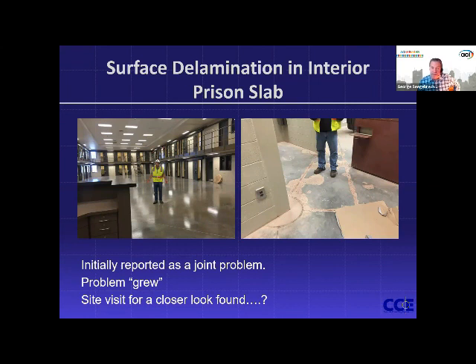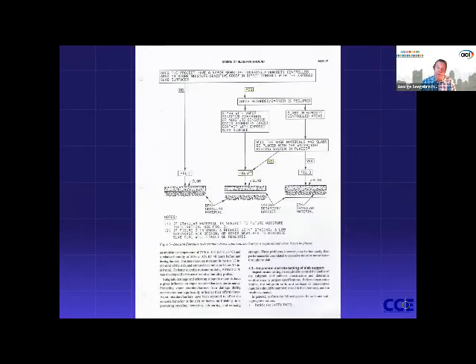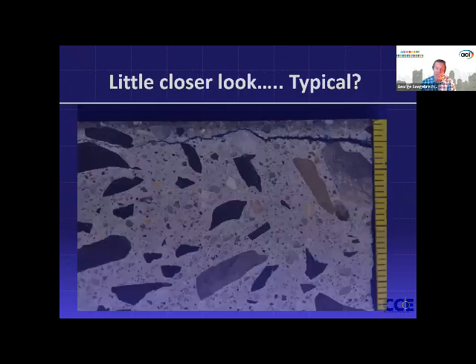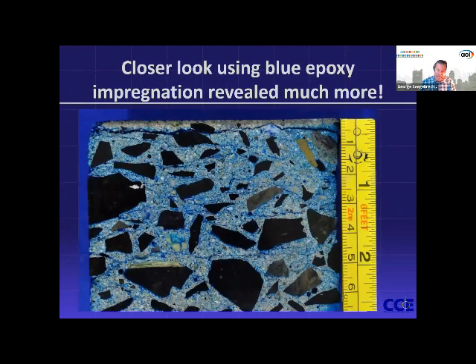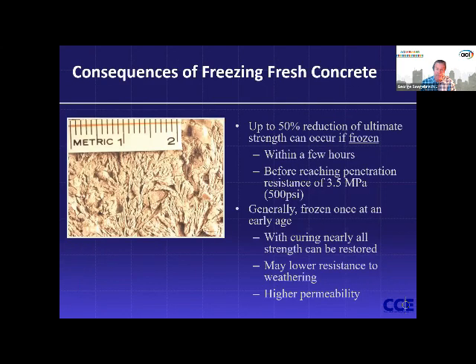And when I first got called about the job, they said, "We have a joint problem." And then they called back a week later, saying, "No, this joint problem's grown." No, it was a delamination problem. That's what started us looking at everything a lot closer. And then we found out that the damage was much more severe than first impression. And I'll just end it at that.